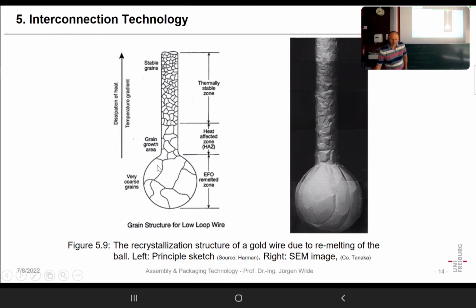So we have larger grains, and that is something we do not really like, because larger grains are always weaker than finer grains. And therefore, Tanaka just did that in order to show how the internal structure is. Of course, you can make a microsection to look inside.